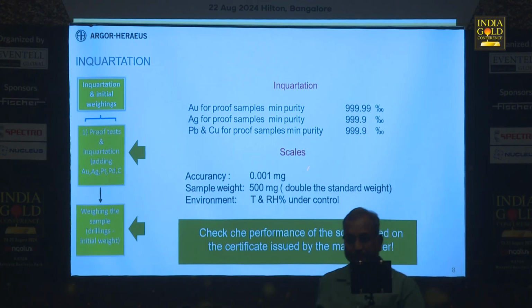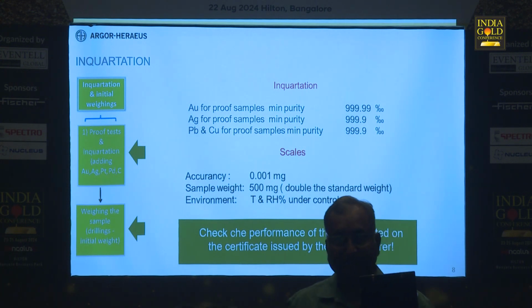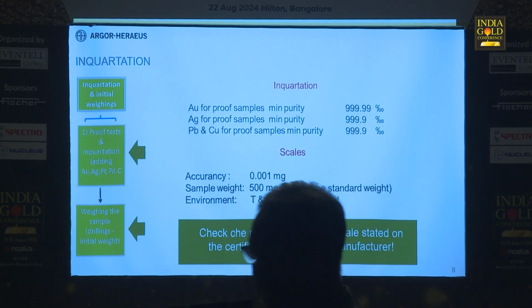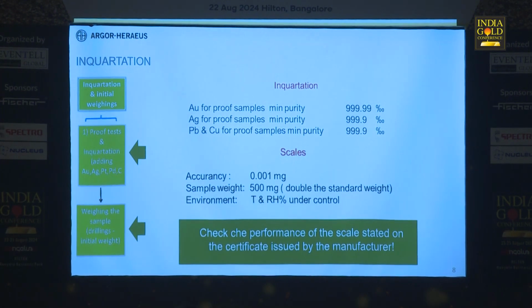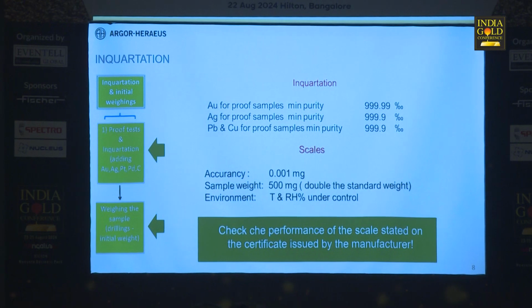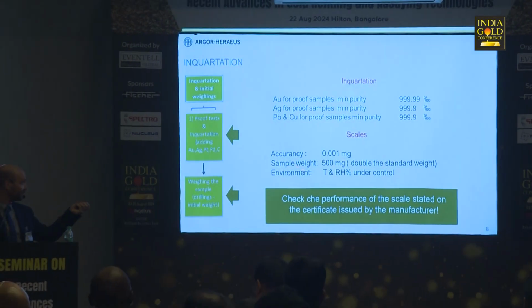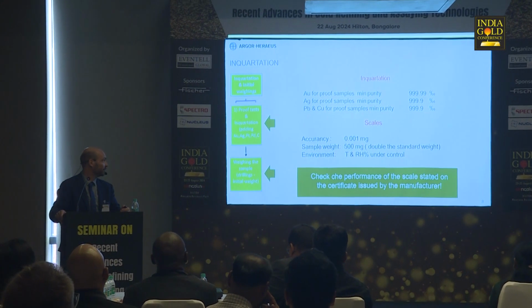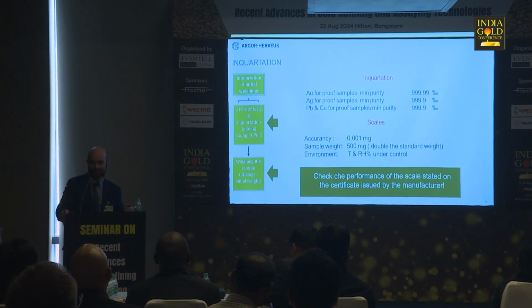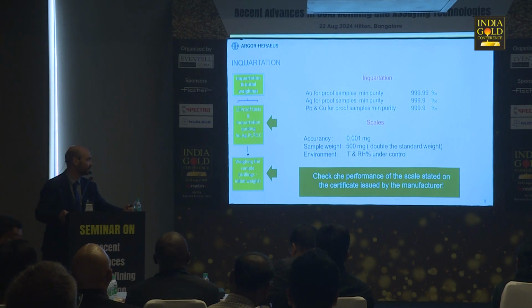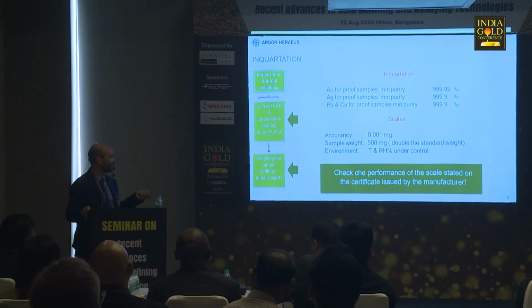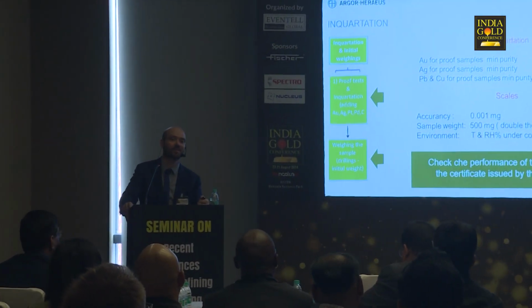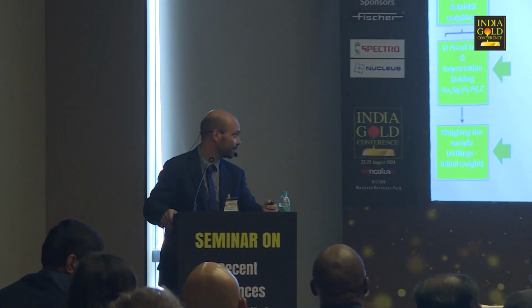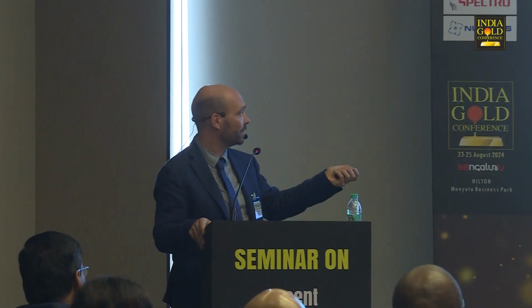Regarding the scales, we need an accuracy of the scales of at least 0.001 milligrams. That means a normal analytical scale doesn't fit for the purpose. We must use some microscales. Regarding the initial sample weight, we must keep it as high as possible because we have a constant error coming from the scale. So a good number could be 500 milligrams. That is double the standard weight that is requested by the normative 11426.